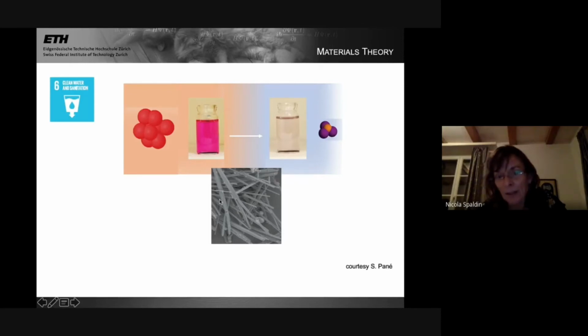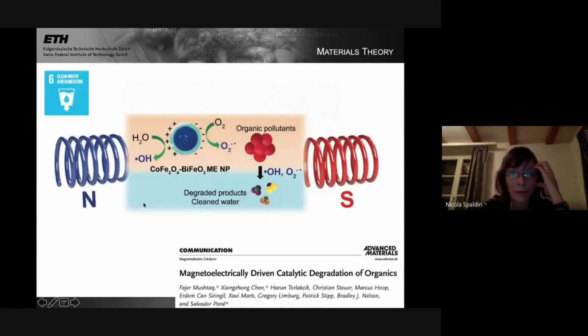So the bismuth ferrite is proving to be rather useful for what's called water remediation, for breaking up nasty organic things into small molecules and purifying the water. And just a cartoon of how it works. This is a nanoparticle of bismuth ferrite, which is both magnetic and ferroelectric. It tends to attract the charged ends of organic pollutants towards it. And then it also will dissociate the water into radicals, which then react with the organic pollutants and degrade them into smaller molecules. And this process can be activated using, in this case, a magnetic field.